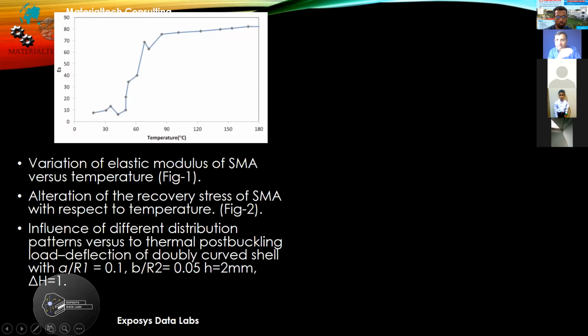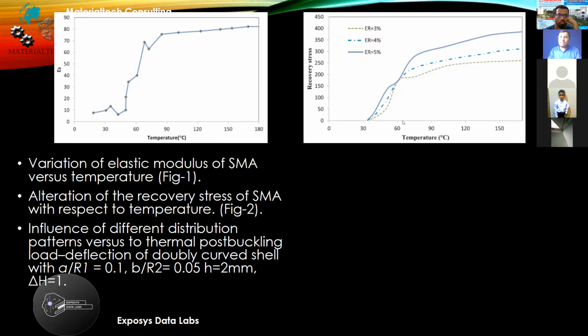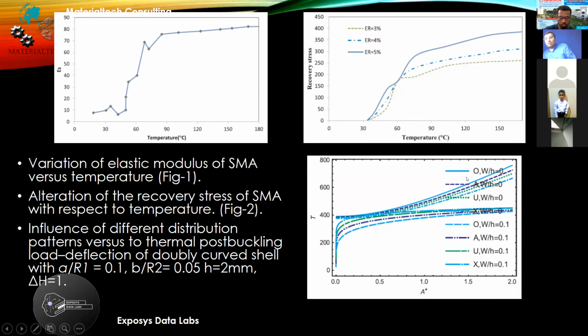In the shape memory effect, we have clearly achieved the shape memory effect with the help of the SMA wires, SMA meshing enhancement. So in the recovery stresses also we have achieved here. With the 3%, 4%, 5% of reinforcements, we have achieved the respective recovery stresses under the influence of different temperatures. Similarly, we have different stacking sequences with the stacking ratio, and for different temperature levels and different curvatures from 0 to 2, we have achieved these kinds of graphs. That is how it exhibits under the influence of different temperature levels. It has given the reverse stressing formation, and that gives you a clear-cut picture of how the re-buckling of the composites can be achieved at those particular levels.